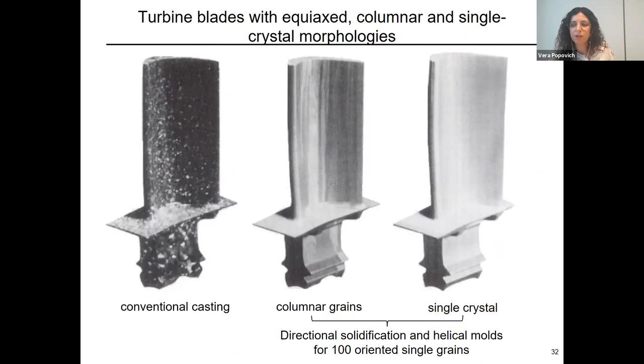It's the 100 orientation, or if you talk about the texture of the grain, it's 001. What happens with the delta sigma, so with the stress, and as a result also the fatigue, when you reduce the Young's modulus by 40%? An example is given in the notes to the slide, so you can have a look. And this is the reason why the thermal fatigue is improved for this kind of grains.